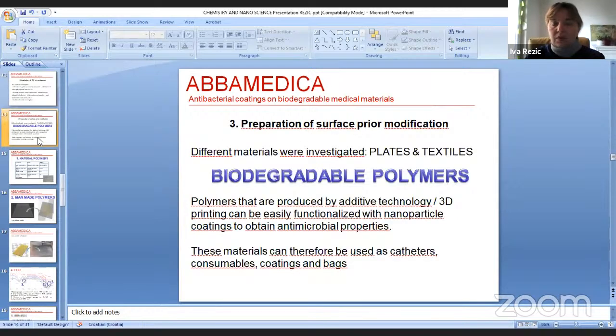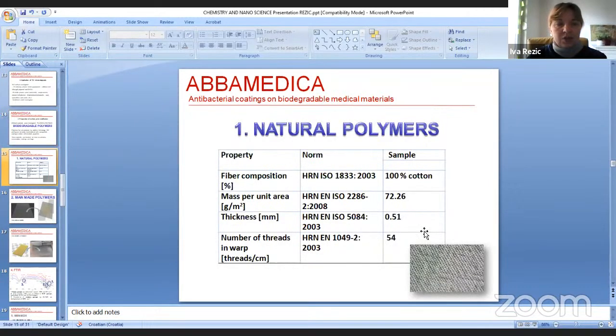The bases were polymers, two kinds of polymers. The first was these 3D printed polymers, which can really easily be functionalized with nanoparticle coatings. And afterwards, you can make all kinds of shapes, so you can produce catheters, consumables, coatings, and bags. And the second kind of material that we are modifying is actually cellulose, textile, woven, or knitted materials. In this picture, you have our sample of textile coating.